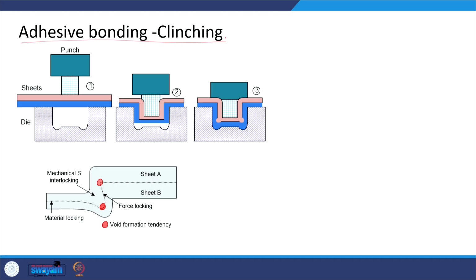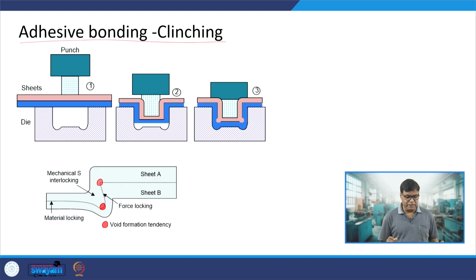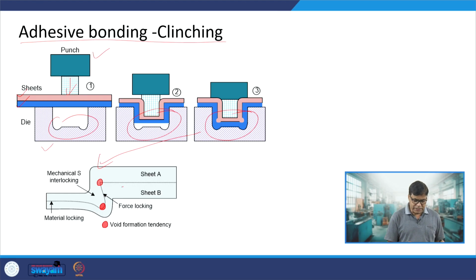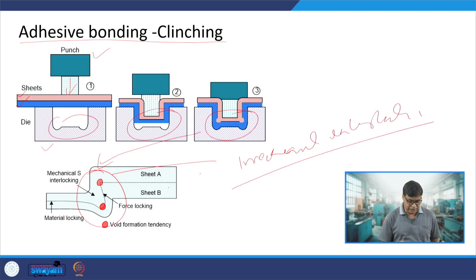Adhesive bonding clubbed with clinching is another kind of mechanical fastening. In this case, we use a die and punch with unique profiles, and the 2 sheets are placed, then the punch is applied. So, here the sheets will be moving down. Okay, when they move down, they get deformed, they fill the gap in the die and they deform like this. When the deformation takes place, in the enlarged view we can see the kind of mechanical interlocking that takes place between the sheets, and this mechanical interlocking will help in development of the desired strength coupled with the adhesives.